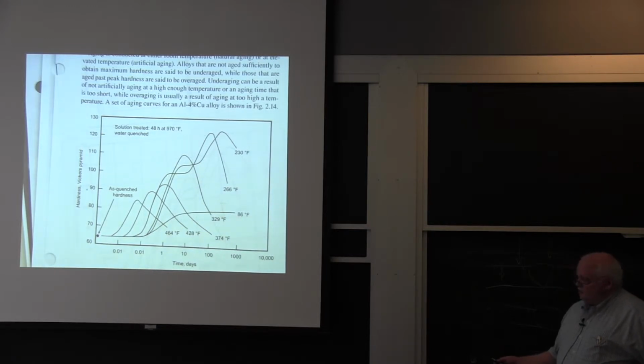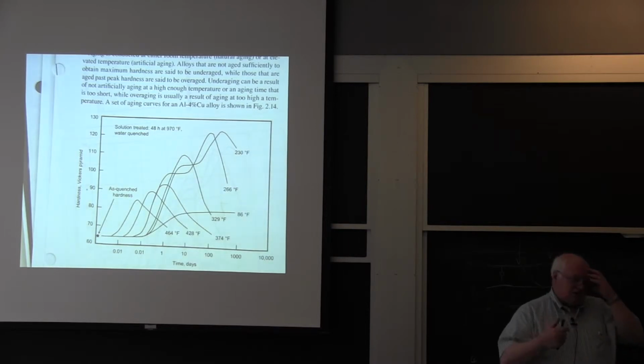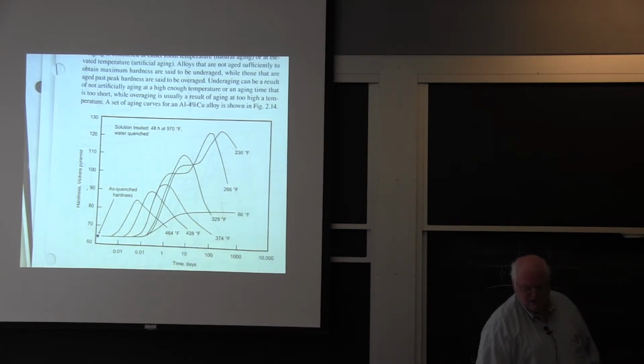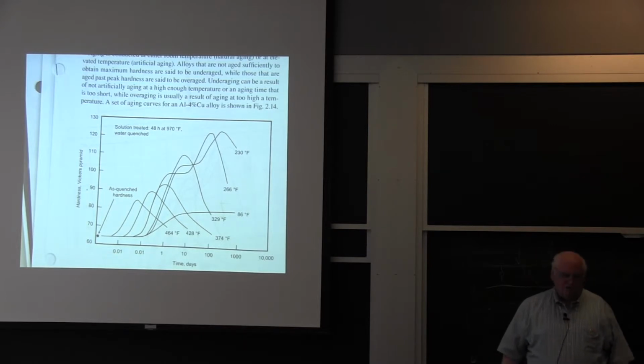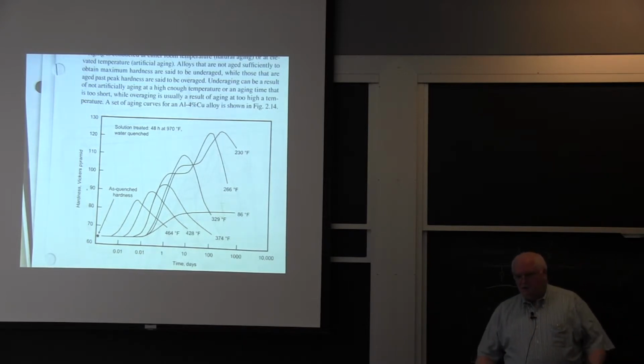So they solutionize these things. If you go to the peak temperature, if I'm at 374, I'm doing my tempering, I can get the peak, that's a T6 heat treatment. I can lose 10% and go over, we call overaging, and lose 10% of my strength, but gain about a factor of 5 in corrosion resistance, okay? So what they had found is, Sikorsky, we did the T6 heat treatment on this other helicopter, we noticed problems with the cracking of the washers, you lose your tail rotor and you can have a bad day.